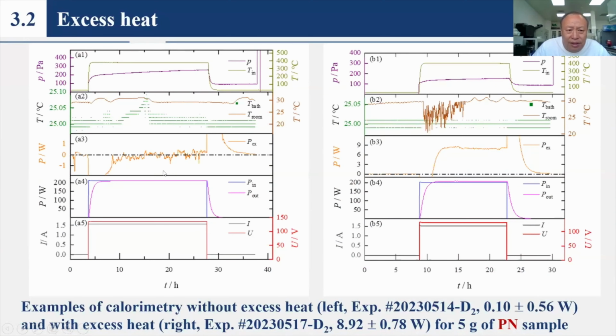Now this is an example of excess heat. The left one is an example of no excess heat. We can find when we applied 200 watts, the measured excess heat is only 0.1 plus or minus 0.56 watt. Three days later, we did the experiment again. This time there is excess heat. Applied power is also 200 watts, and the excess power is 8.92 plus or minus 0.78 watts. This is for the PN sample, about 5 grams.